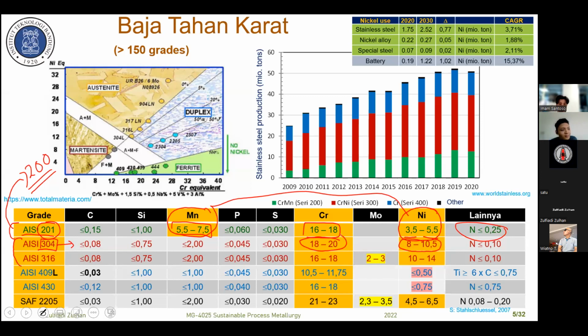And 316 is more or less similar to 304. The difference is that molybdenum is added to the 316, and also the nickel content is increased to a minimum of 10%. The other steel grades are the 400 series, what we call ferritic stainless steel. In this stainless steel, usually there's no nickel. The nickel is close to 0%, so we do not add any nickel there. In some grades, the nickel content is less than 4 or 5%. And the last one is duplex stainless steel.